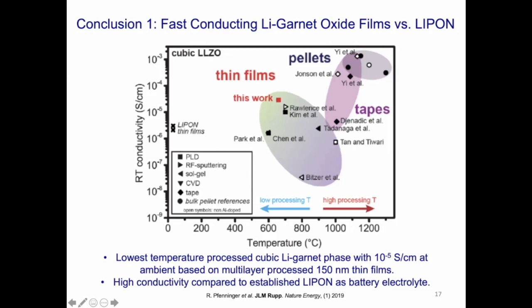And what's also exciting is that you can see here the temperature reduction in manufacture from above 1000 to around 650, while still being in a thin film structure overall. And after our publication in 2019, I was thrilled to see that there have been several follow-up groups. For instance, Jordi from Empa demonstrated, using a similar sputtering approach, even higher conduction. So this is really translatable to several labs all over the world right now as a technique.